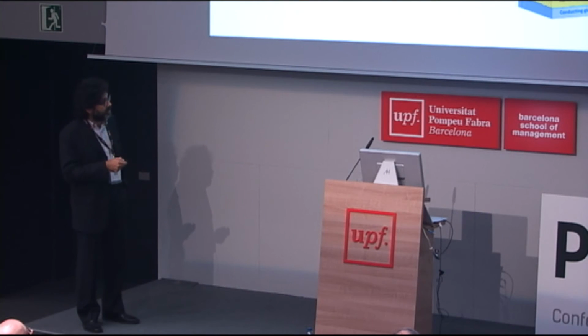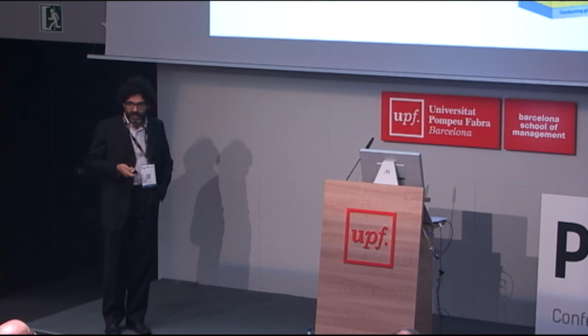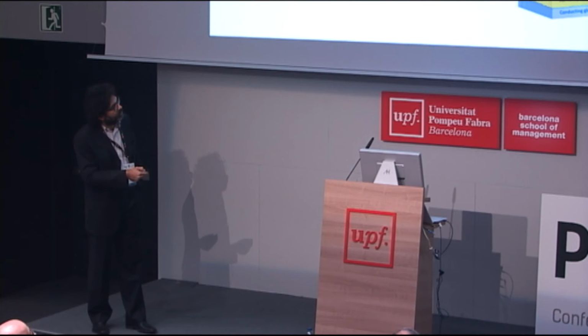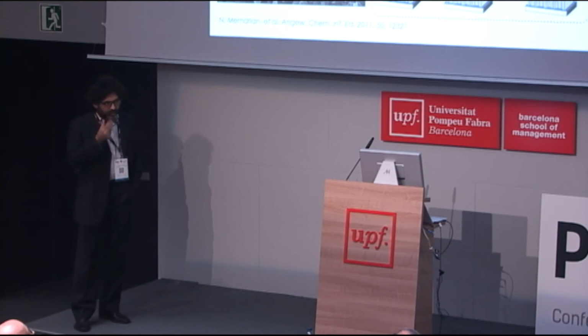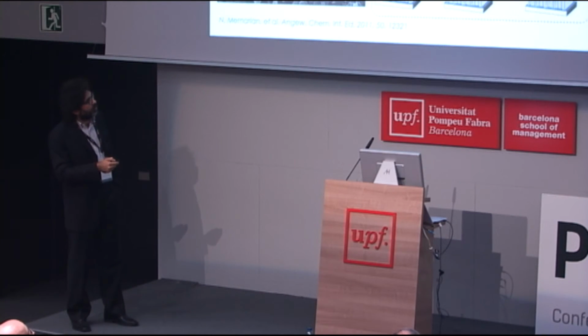We tried to get these kinds of systems through a very simple process of spray deposition, and we also applied a pretty thick buffer layer of zinc oxide to inhibit the back reaction from the conducting glass and the electrolyte. The results were pretty nice because we were able to get these microstructures composed of very small nanoparticles. It's still not clear why, under annealing, these large crystals form these hierarchical structures during the firing process, as you can see here.